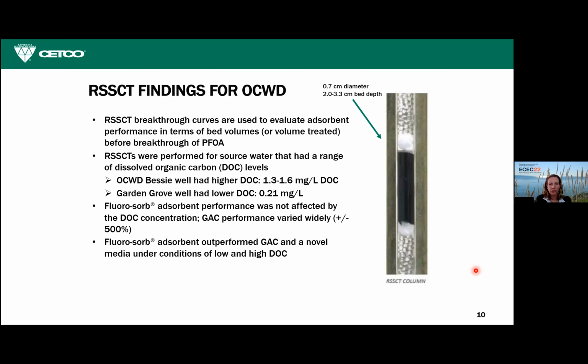Orange County Water District compared a high DOC, or dissolved organic carbon, water, the levels are shown here, to a low organic carbon water, because even small increases in dissolved organic carbon can cause problems for GAC adsorption of PFAS. What they found was that Fluorosorb was not affected by the DOC concentration, and Fluorosorb was able to outperform the GAC in the high and the low DOC conditions, but in the high DOC condition, it was a significant improvement.